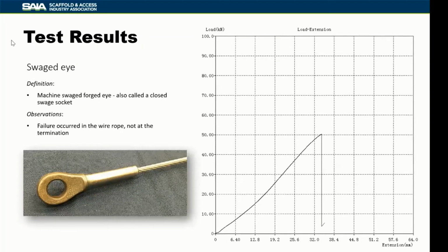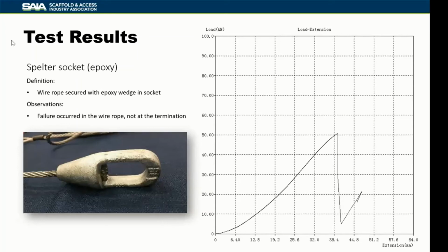Looking at a mechanically swedged eye, again the failure occurred in the wire rope, not in the termination, back to that 50 kilonewton range, or the 11,000 pounds of force. The elongation was slightly less, probably a 1/4 inch less than in some of the other ones. The Spelter socket again performed very similarly to the mechanical swedges and many of the others, with about 11,000 breaking force and elongation in the 1.5-inch range.